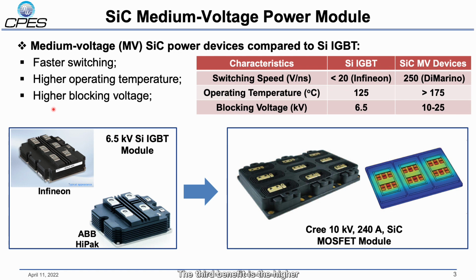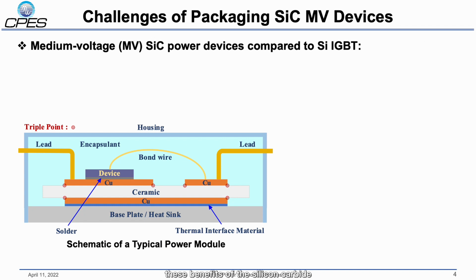The third benefit is the higher blocking voltage of the silicon carbide medium voltage power devices. For silicon IGBT, it usually can only block 6.5 kV. However, for silicon carbide, it can block from 10 kV up to 25 kV. However, these benefits of the silicon carbide medium voltage power devices are also challenging the packaging and the material selection in these power modules. This picture shows the schematic of a typical power module.